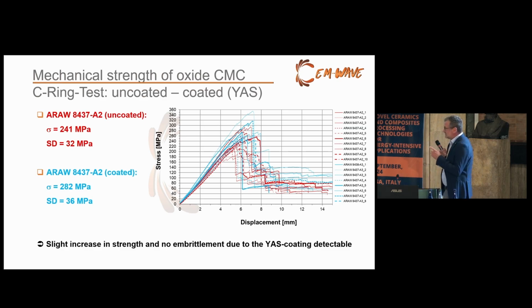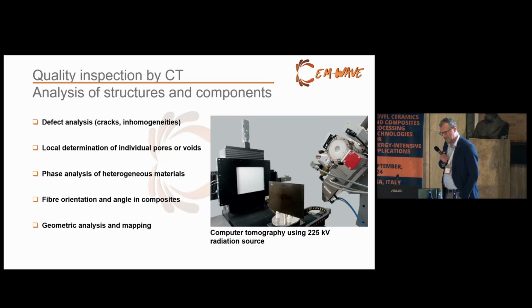But normally it's maybe not just an increase, because when you test this kind of system with the coating, you should also test your oxide material without the coating, but following all these high temperature sintering techniques, and maybe then you would have the same strength at the end. However, there is no embrittlement, which can of course occur. We didn't see embrittlement through the YAS coating, which occurred in this oxide system at 1150 degrees C, and this is a nice thing, that nothing happened to the CMC, because most of the time you really get a worsening of your strength due to the processes.